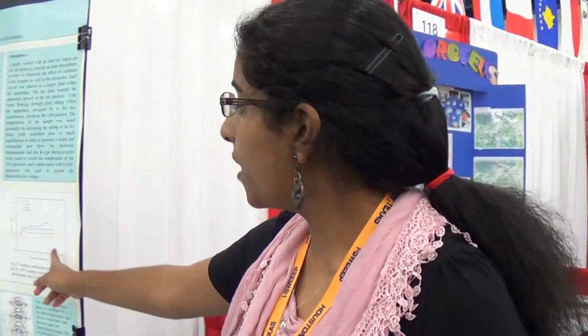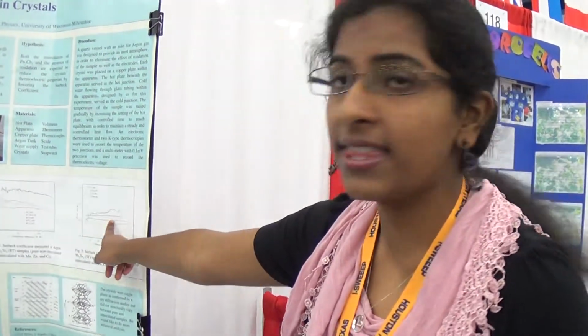And this is a simple but very important observation, because one thing that we thought of as we were doing our experiment is that it's not possible to generate a perfectly pure crystal in our world. I mean, in an ideal world, sure, that could be a possibility, but impurities are everywhere and they can easily get into the synthesis process of these crystals. So this trend that we saw in the antimony telluride system gave us hope, because it showed us that even with the introduction of impurities, a simple increase in the temperature difference should be able to override the effect of impurities and therefore generate just as much voltage as a pure sample would.